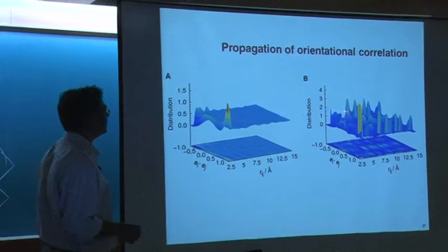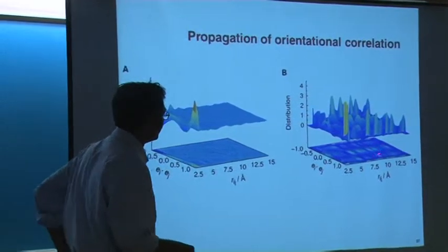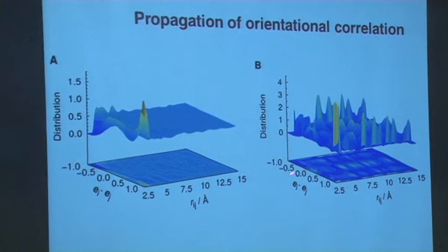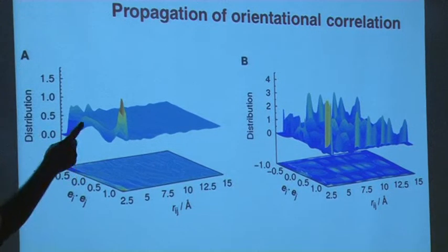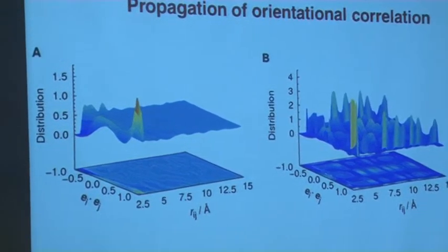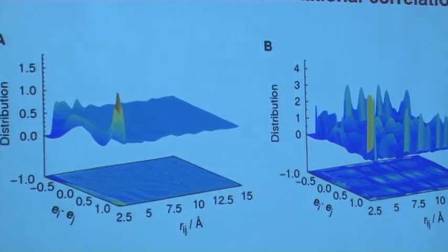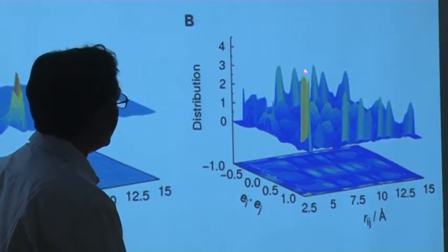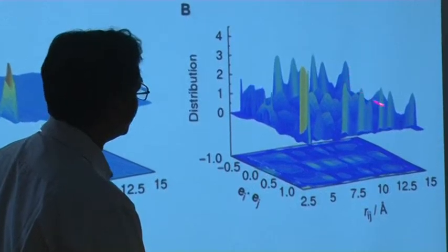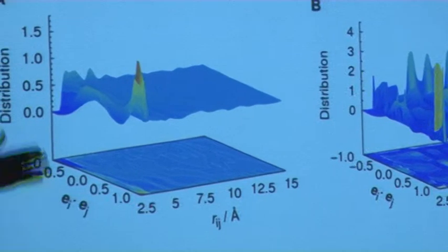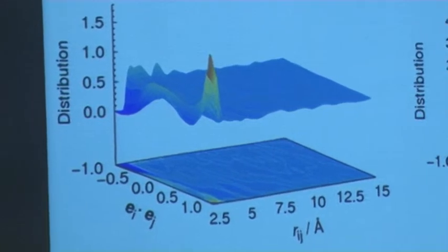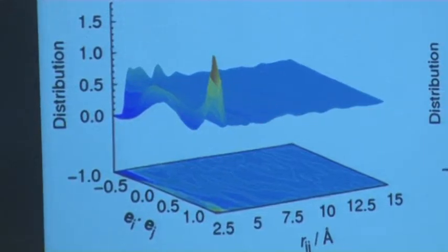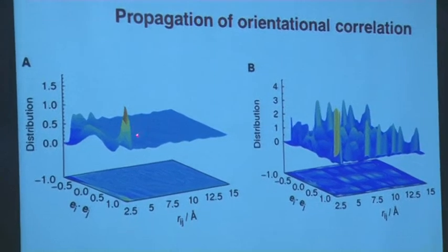This is the difference between amorphous ice and real ice, the ice that you form in your refrigerator. What I have plotted here, orientation, theta is an angle of one tetrahedral with another tetrahedral, and this is the distance. In ice, you see how correlated they are. The peaks are in definite crystalline hexagonal lattice positions. Amorphous ice, which is at 100 or 120 Kelvin, look at, there is no propagation. Their densities are fairly close to each other. But amorphous ice, no propagation of orientation correlation.